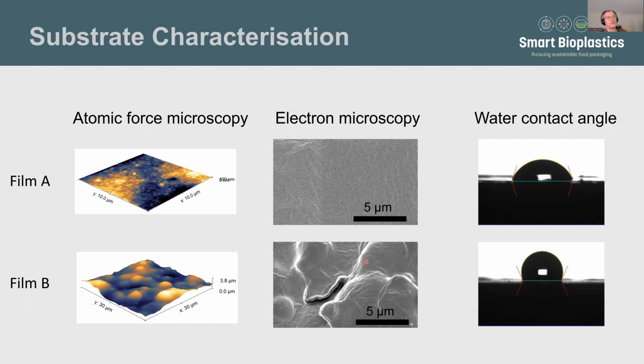But it surfaces also a different attribute, and that comes about the spraying itself. How do you create even films in coatings onto those films? And again, if you're looking at film B for now, here with the water contact angle, you'll see we have a very distinct bubble forming with a very steep angle.